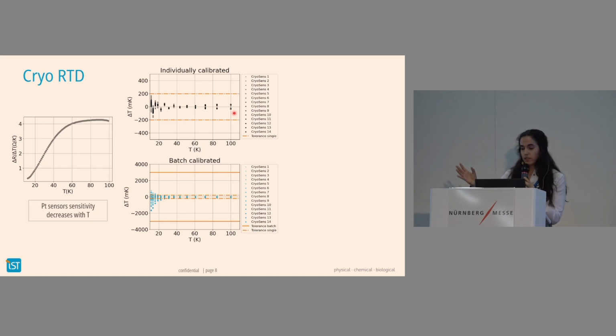What is now part of the core knowledge is to extend this calibration that we did for just a few sensors to the whole batch. So like to control actually the conditions and the impurities that we have in the platinum to actually be able to use this for the whole batch. So this is what we did in the second plot. Here are the so-called batch sensors, and this is the accuracy that they deliver. So as you can see, also above 20 kelvin is extremely good.